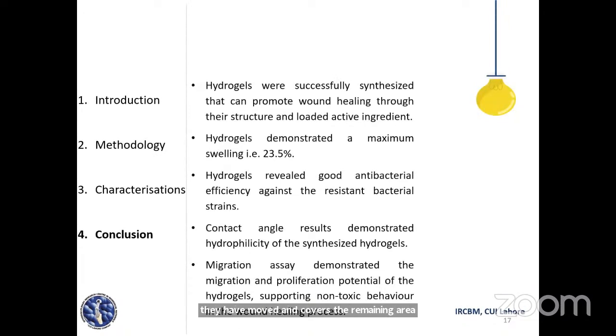In conclusion, I would like to add that hydrogels were successfully synthesized that promoted wound healing through the structure and loaded active ingredient. Hydrogels have demonstrated a maximum swelling of 23.5%, and they have revealed good antibacterial efficiency against the resistant bacterial strains. The contact angle results have demonstrated hydrophilicity of the synthesized hydrogels, and migration assays have demonstrated the migration and proliferation potential of the hydrogels, and they have supported the non-toxic behavior in the wound healing process.